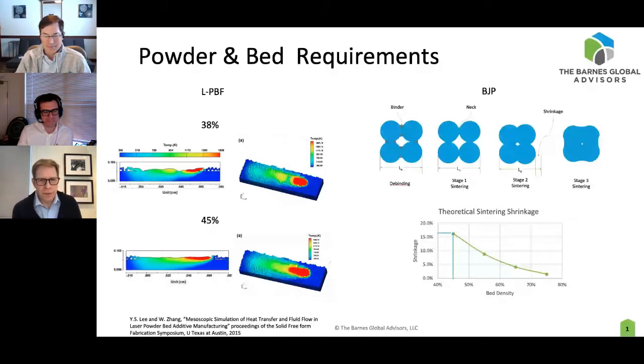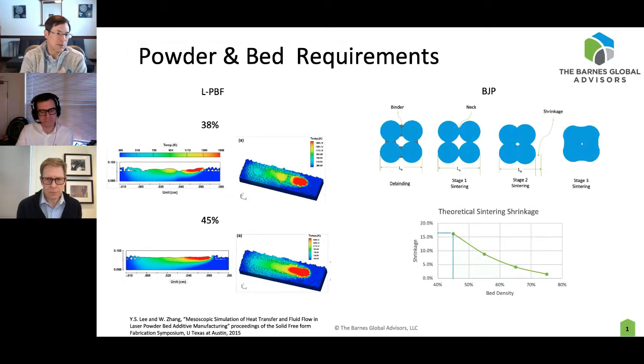So lastly, Kirk, talk to us about the 38% and 45%. Right, so that's work from Lee and Zhang at UT Austin, looking at a simulation of powder of different size and shape fractions randomly distributed in a bed at 38% density and 45% density. If you look at the melt pool on the right for the 38% case, it looks like there's starting to be a balling defect. You can see that in the cross-section view on the left, that the melt surface is really kind of cranky. If you increase the density of the randomly distributed particles to 45%, then you get a much more uniform melt pool and a much more uniform surface topology.